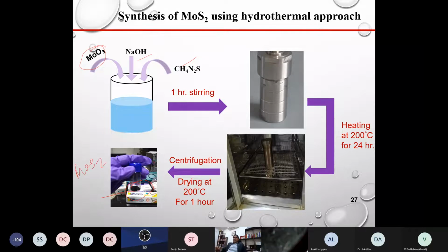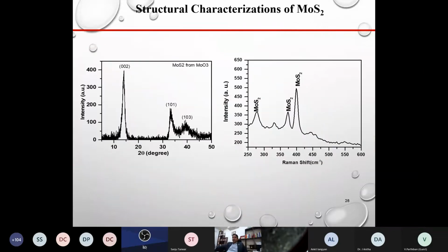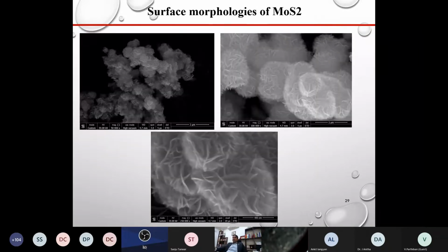So the first thing is whether this black powder is MoS2 or something else. We have to characterize it. We did Raman spectroscopy and X-ray diffraction, and from both these techniques we found that this black material is MoS2. Next, we took the electron microscopy images, and you can see these very nice